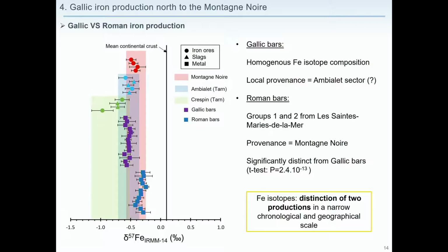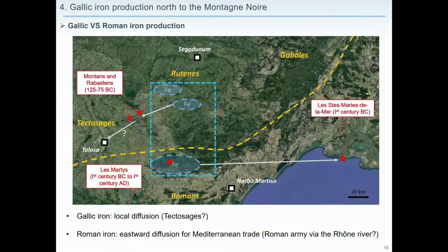And maybe more interesting here, if we compare the composition of the Gallic bars with that of the Roman bars, a simple t-test shows that they are significantly distinct in composition. So in this case, the iron isotopes allow distinguishing two iron productions at very narrow chronological and geographical scales, because at the same time we had in the south, in the Montagne Noire, a Roman iron production destined for the iron trade in the Mediterranean Sea, and at the same time we have a Gallic iron production here, which was most likely destined for local diffusion.